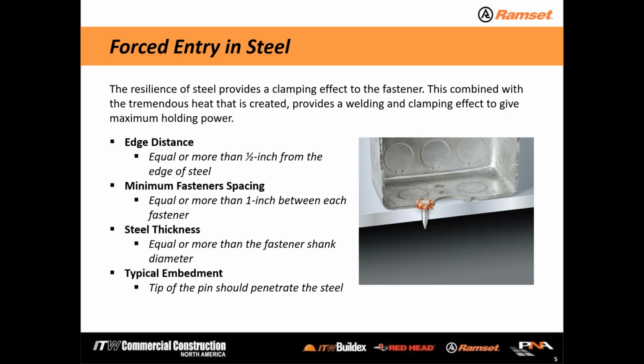Fastener center to center spacing, again, is about 1 inch. So again, if you install a fastener, you want to move over enough to where you can close the tool and not interfere with the previously installed fastener, and that's roughly about 1 inch. We want to make sure that we don't impede on the other fastener in the installation.